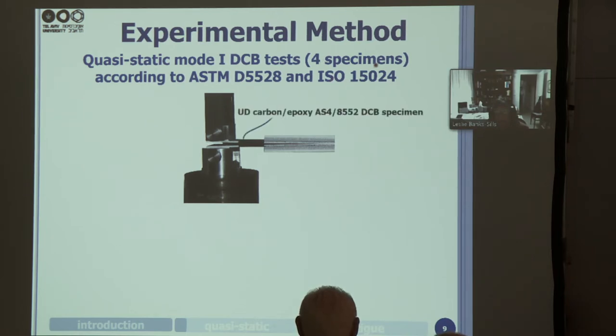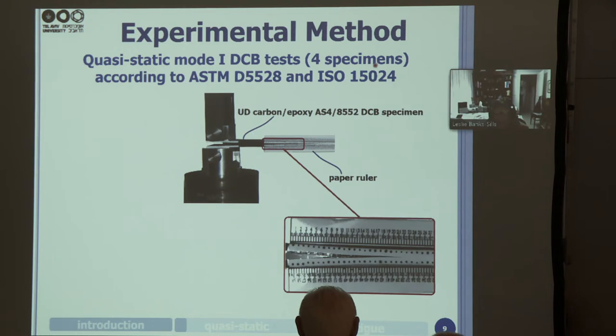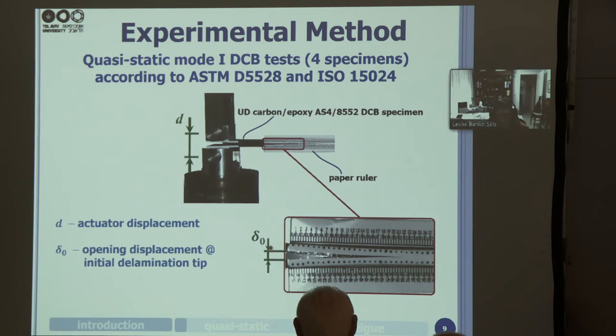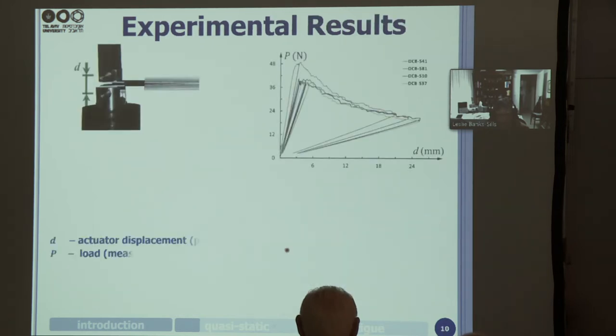tests on four specimens, and the specimen is shown, and we blew on a paper ruler, so you can see now that we can follow the delamination tip, and we capture images with a LaVision camera system, and so we can follow the delamination as it propagates, and we can also follow, and you can see, I hope, the fiber bridging zone. So D is the actuated displacement, and delta naught is the crack opening or delamination opening at the initial delamination tip. And delta A is the crack length extension or delamination length extension.